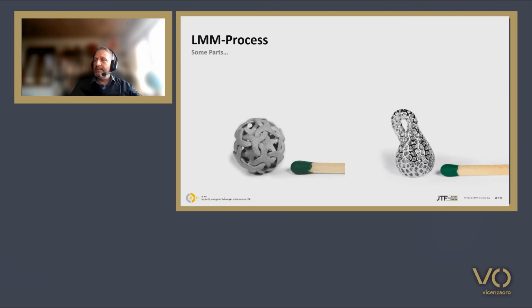Here on the left side, a representation of this ball, which has inner structures. And because of the shrinkage of the material, one can also imagine that it could work together with some inlays that one puts in. The restriction obviously is that it has to go through the sintering furnace. So if you put in, for example, a precious stone, it has to be temperature resistant to the sintering. On the left side, a part only tumble polished. So you see that the surface is really very good and also allows glossy structures. If it were hand polished, even more.